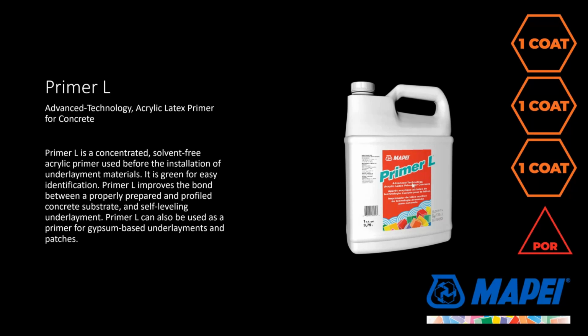This is the product we recommend almost 100% when dealing with gypsum underlayments, like poured gypsum floors in residential home projects. There are some specific instructions on how to use Primer L under those applications, and that is to use a broom to push this on the floor, not a roller. We like that broom to go over these gypsum substrates to help break up the friable surface on the top, allow the Primer L to penetrate and really give that great bond. It doesn't work all that well to use a roller to put the primer on top of this because you're sticking to the dust and not getting into the meat of the underlayment. But again, highly recommend you take a look at the TDS next time you're involved in that.